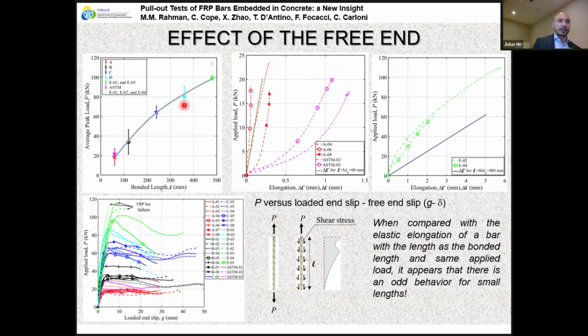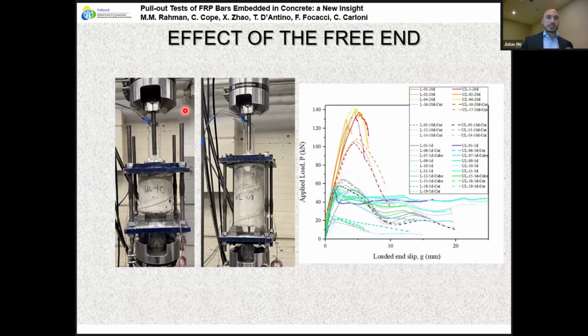And I should mention that for the fourth length, we didn't actually have those specimens. We cut them from longer specimens, so these specimens did not have the protruding part, the free end part that was sticking out. So we decided, is it possible that the protruding part has that effect? So we recast with a new bar.